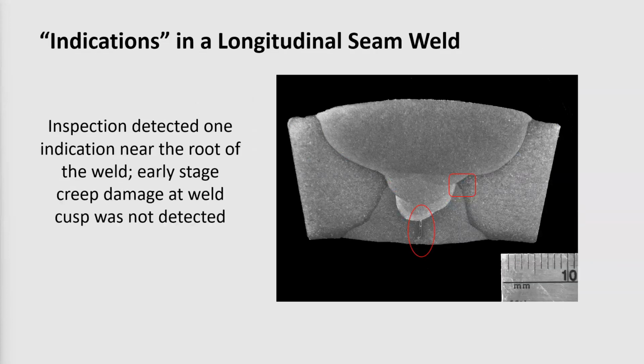Let me give you a few examples of some of the complications that may arise when you're doing these inspections. These are mostly taken from long seam welds only because there have been so many inspections of long seams. But again, these same issues would hold for other welds also. So this was a case where inspection did find an indication near the root of the weld.